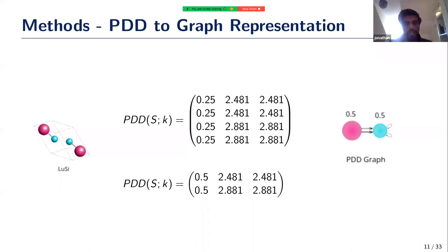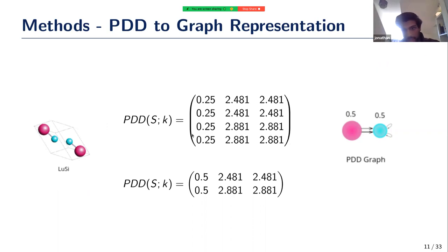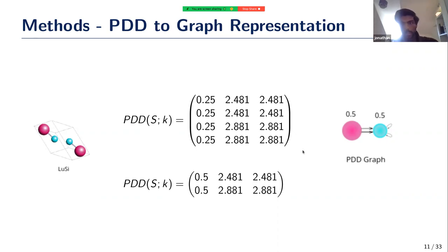Here is a simple example using lutetium silicon. With four atoms in the unit cell, we have four rows in the uncollapsed PDD, with distances to each atom's first and second neighbor (k equals two). The first two rows — corresponding to lutetium — are identical, and the second two rows — corresponding to silicon — are also identical. These can be collapsed and their weights are added. The final PDD graph has one node per row, with directed edges for each entry.